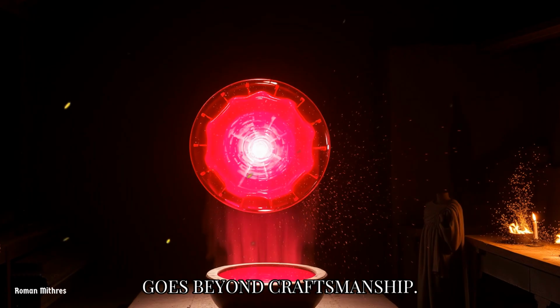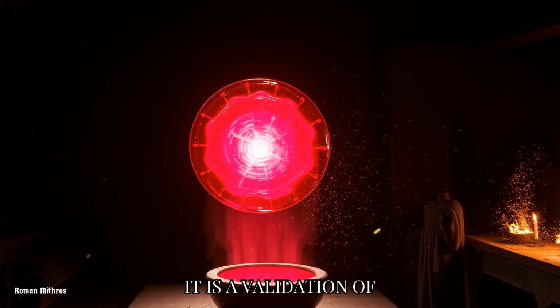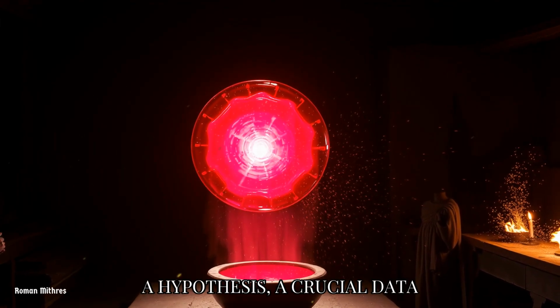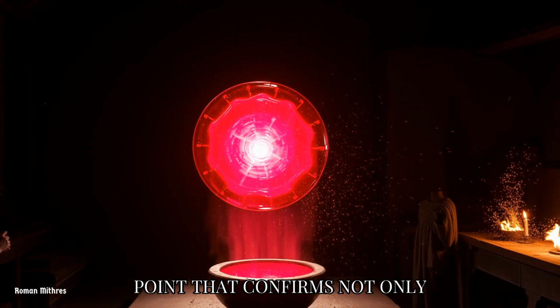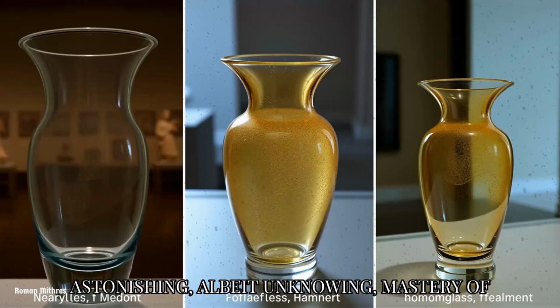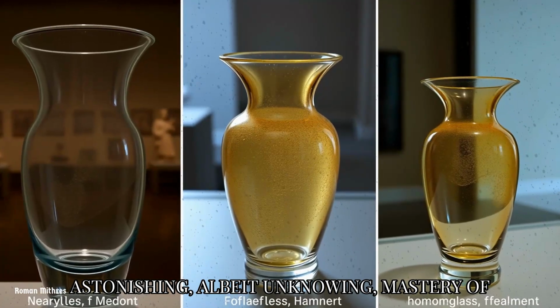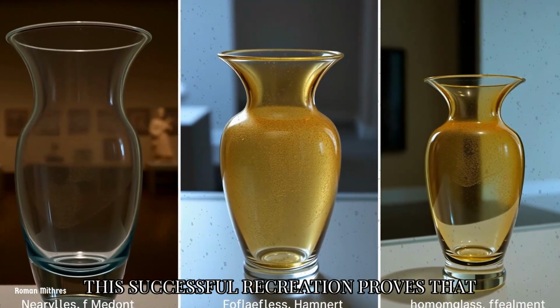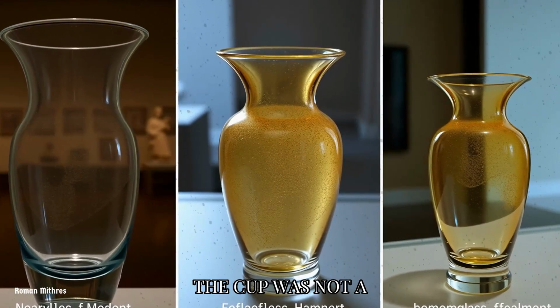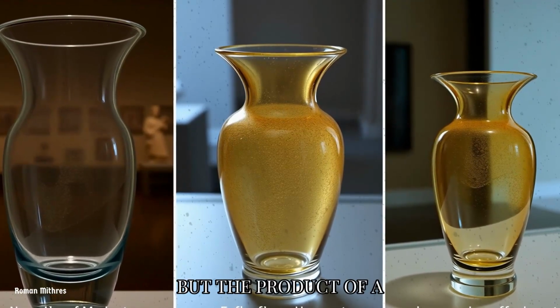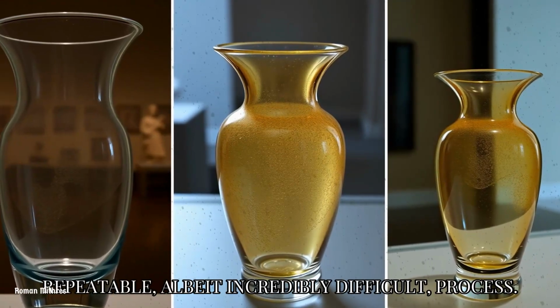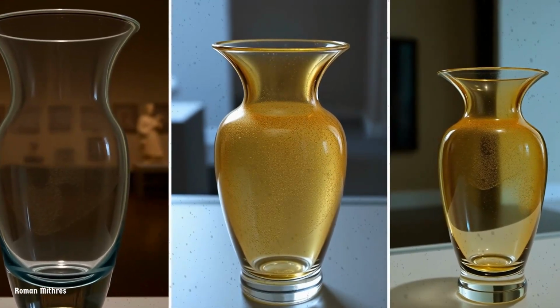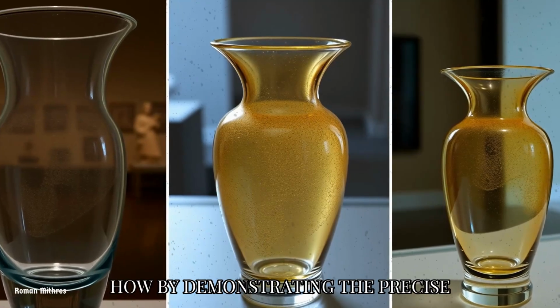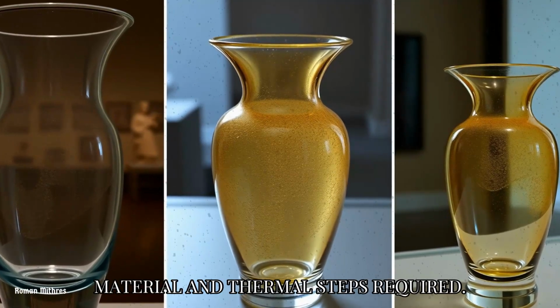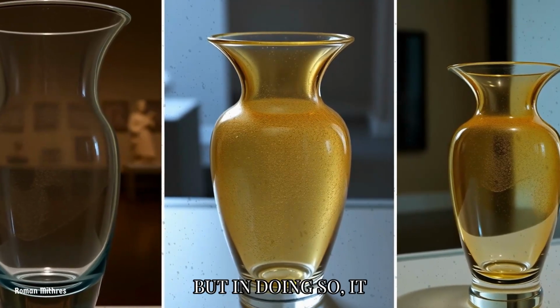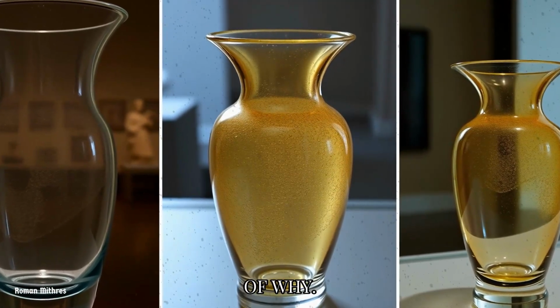It is a victory that goes beyond craftsmanship. It is a validation of our hypothesis, a crucial data point that confirms not only the recipe but the Romans' astonishing, albeit unknowing, mastery of nanoparticle physics. This successful recreation proves that the cup was not a one-off fluke, but the product of a repeatable, albeit incredibly difficult, process. It solves the mystery of how by demonstrating the precise material and thermal steps required. But in doing so, it deepens the even greater mystery of why.